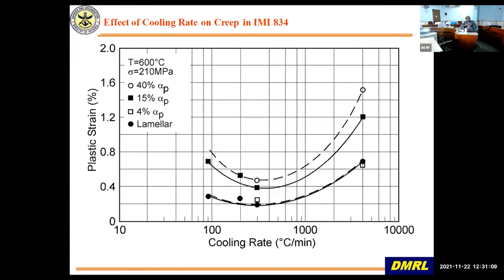Then about heat treatment, you have to be careful. You see, either the faster cooling rate after solution treatment or annealing treatment, or a slower cooling rate, both deteriorate the creep properties in all kinds of microstructure. That is, this is the temperature and stress applied, and this unfilled is for 40% primary alpha. These boxes are for 15% primary alpha, and this is for lamellar structure. The lamellar structure creep is best, but again, intermediate cooling gives you the best creep properties. This is for certain regions. I will again not go into too much detail about this, but you have to remember that heat treatment plays a major role in optimizing the creep properties.